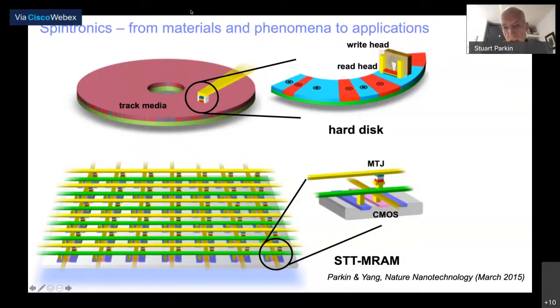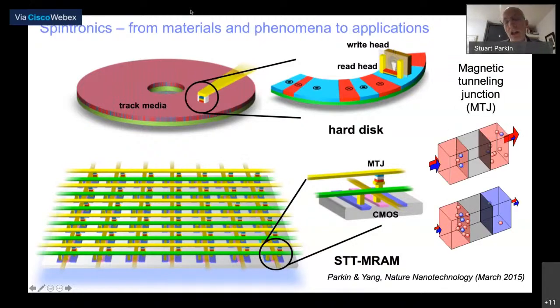Well, this spin valve sensor, a metallic sensor, lasted for about 10 years and was replaced in 2007 with its successor, the tunneling junction device, which is shown here. And a tunneling junction is a simple sandwich of 2 magnetic layers, shown here in red and blue, separated by a very thin insulating layer. And the electrons tunnel across this insulating layer.